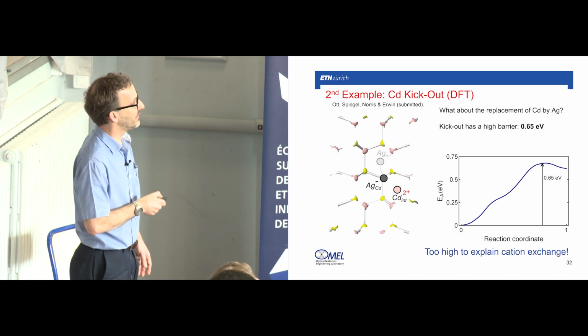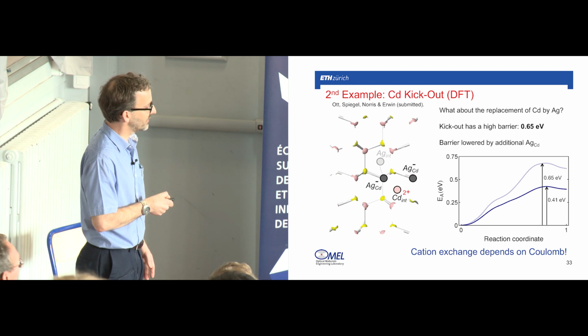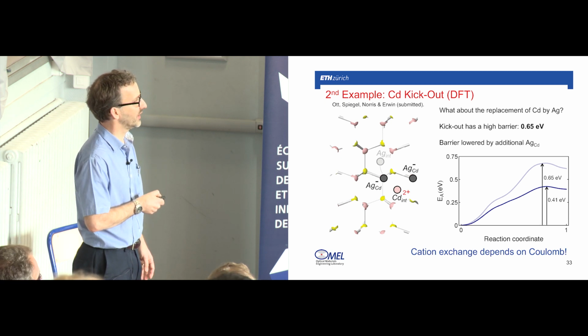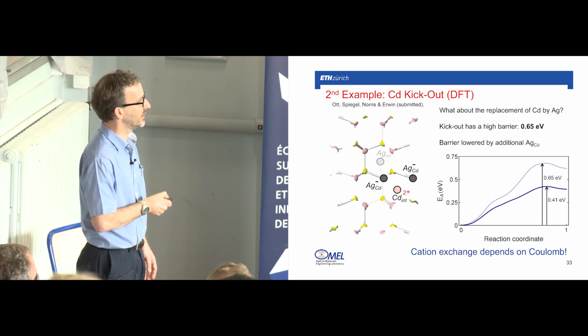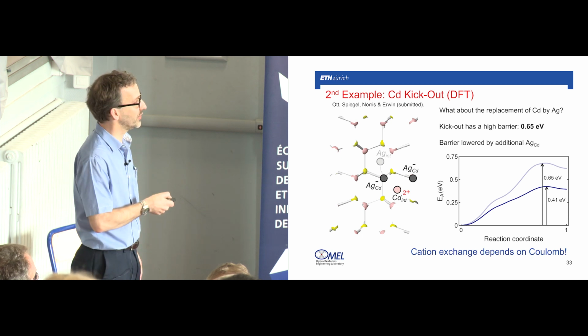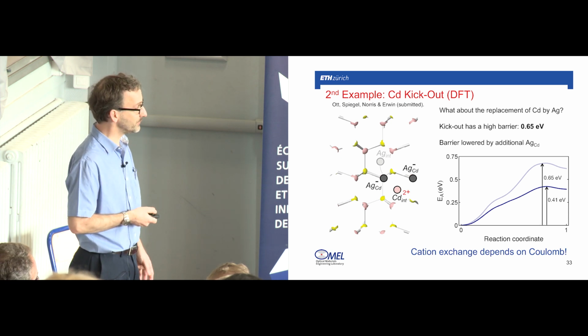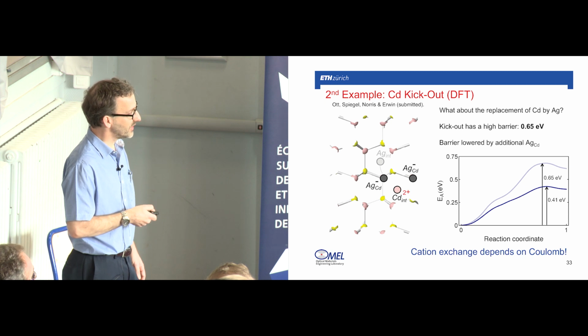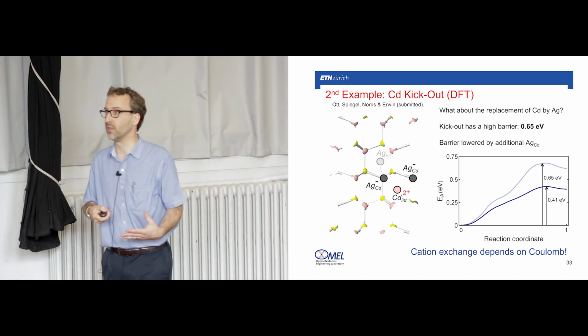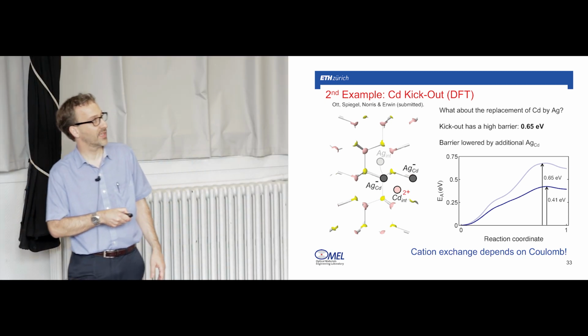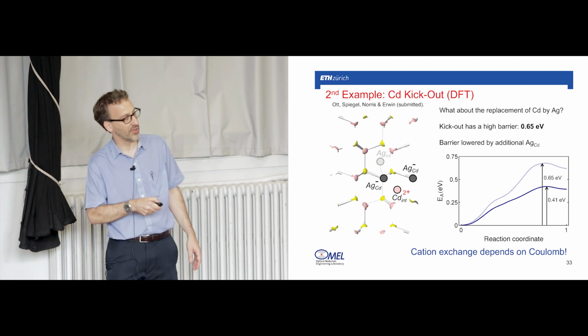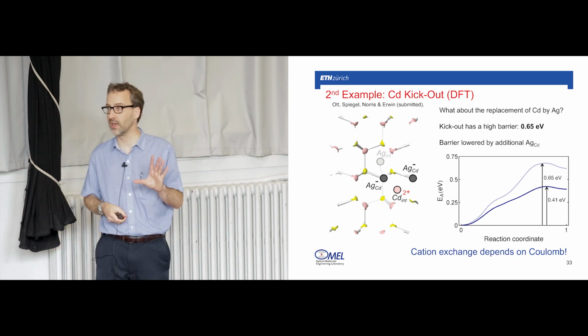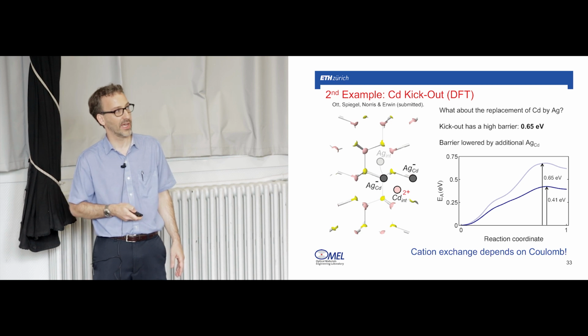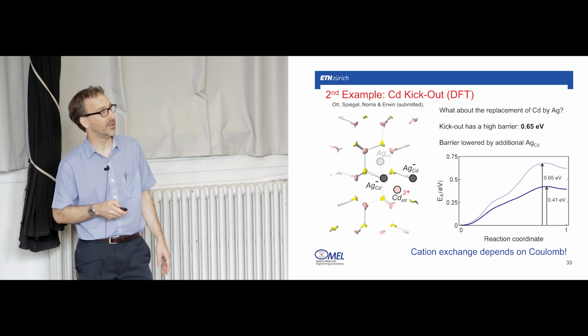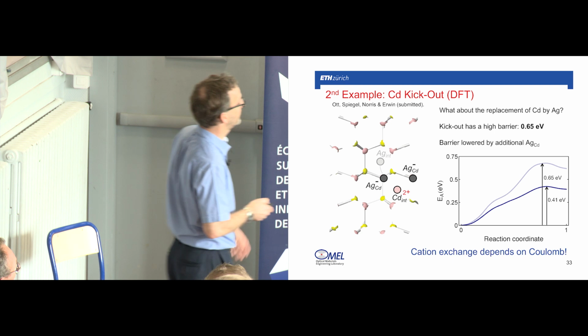But if you now add the premise that you already have a substitutional silver that's negatively charged, this can help stabilize all of these ions, all this charge, and you can lower the barrier by 0.25 eV, and this speeds up the reaction by 4 orders of magnitude. So just this Coulomb interaction here can explain cation exchange. Cation exchange really relies on these interactions, and I'll show you that in a simulation right now.